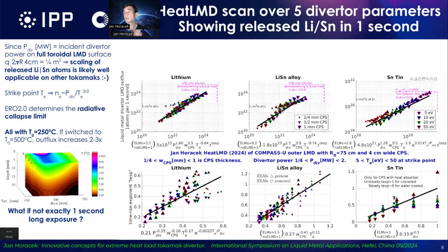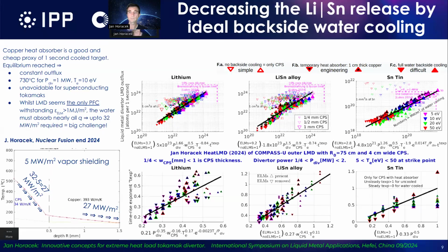It means that 1 second plasma is quite the same as if you cool it down perfectly using water. But this also shows us that if we want to use it for steady state, like running it not for 1 second, but hours and years, we need, of course, the water cooling. But in this case, the amount of energy which has to be released from the backside is really huge. These are these numbers in megawatt per square meter.